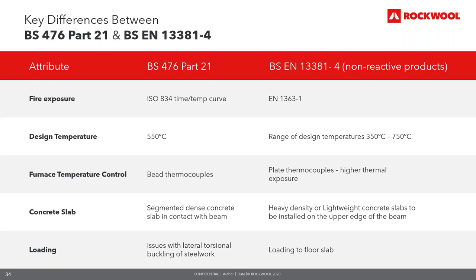Therefore, tests in furnaces controlled by the larger plate thermocouples will be much more severe than those controlled by the smaller, more responsive bead thermocouples, although both nominally follow the same time-temperature relationship.